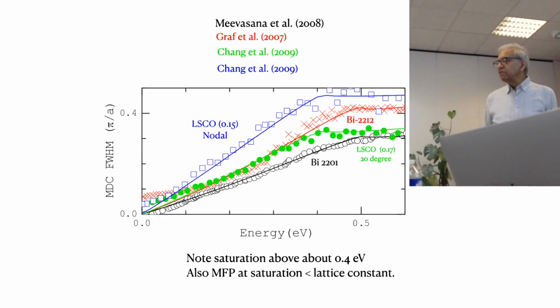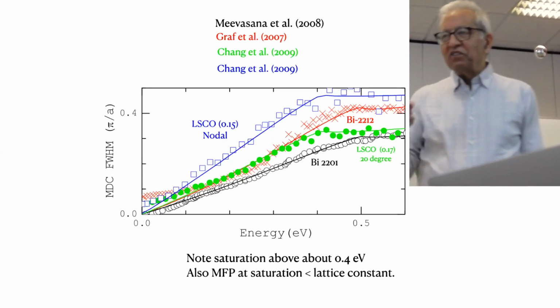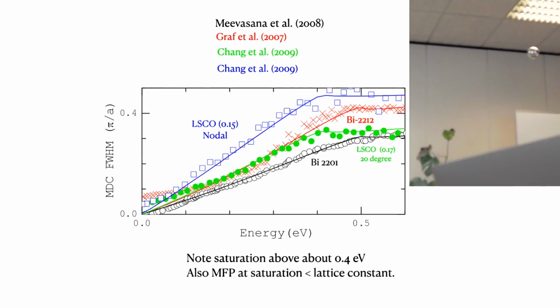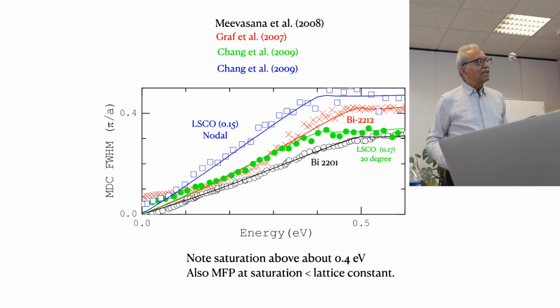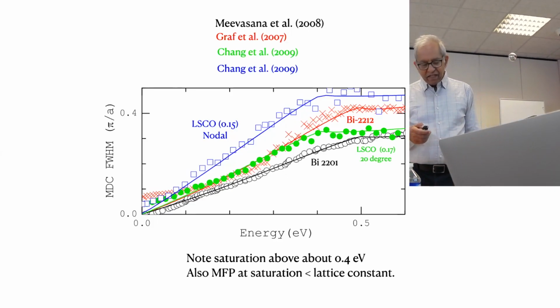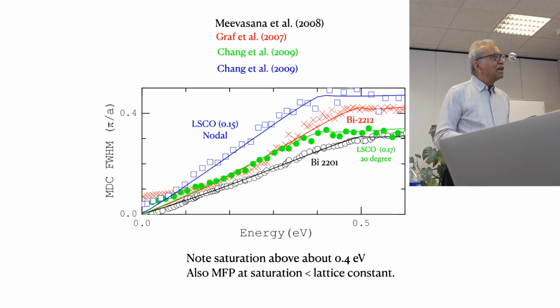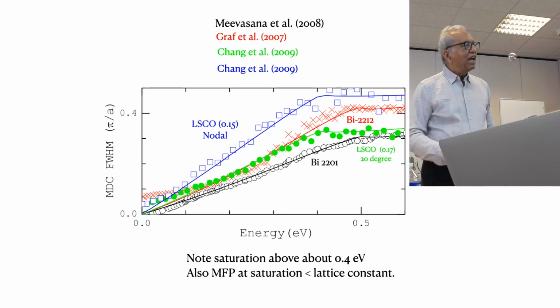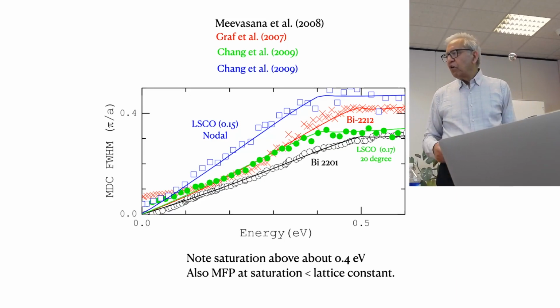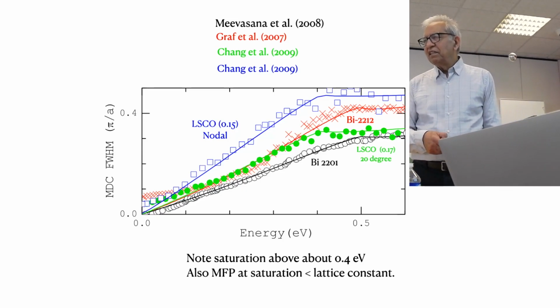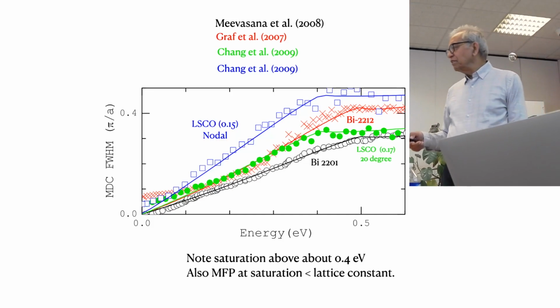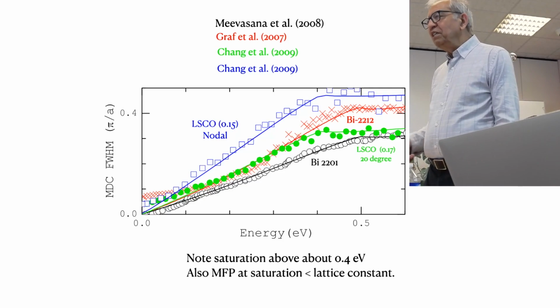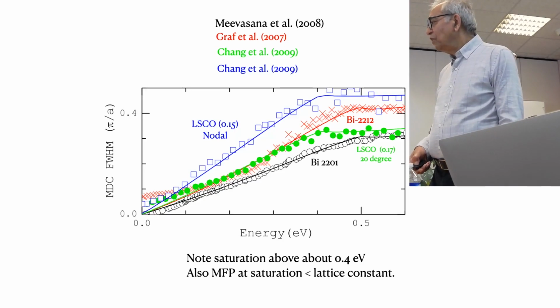Okay, so I mentioned this thing about linear scattering rate. Certain things can be done systematically to low frequencies. This came about through technical developments in angle resolved photoemission. And this is the momentum distribution curve half width normalized to the Brillouin zone size as a function of energy at some temperature of the order of about Tc, okay? And then you have measured it to low energy, and this is predicted to go as T for T larger than omega, and to go as omega for omega larger than T.